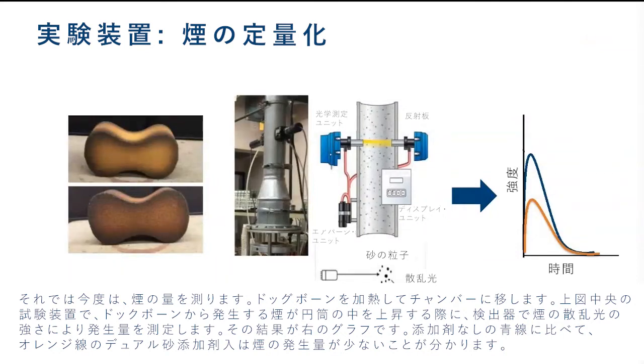When the smoke, due to the core present, starts traveling upwards, the incident light will be scattered by the particles and anything that will be blocking the incident light. For that reason, like a physics concept, you will have scattered light, which is what will indicate the amount of smoke present in the experiment. So when you record this, you measure the intensity of the scattered light as a function of time. This blue curve here is just a cartoon to understand the data. The blue curve means you have a core specimen that had higher smoke, and the orange curve means less smoke. That's the kind of data that we'll generate from these experiments.